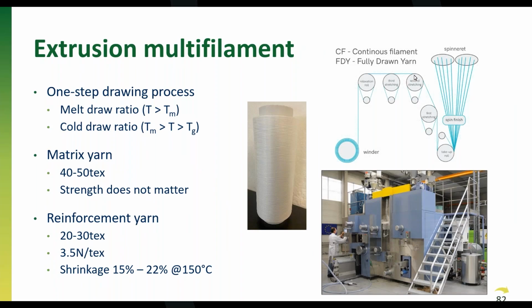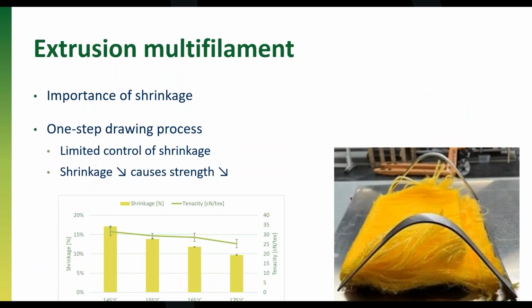Within this one-step process, we are a little bit limited in controlling the shrinkage, and on the right hand side you can see a first glance of why shrinkage is important. It is because we do a filament winding step, we heat the yarns, but then they shrink and they just in this case bend the tooling for the composite formation. Hans will tell more about that, but this is already why shrinkage is very important.